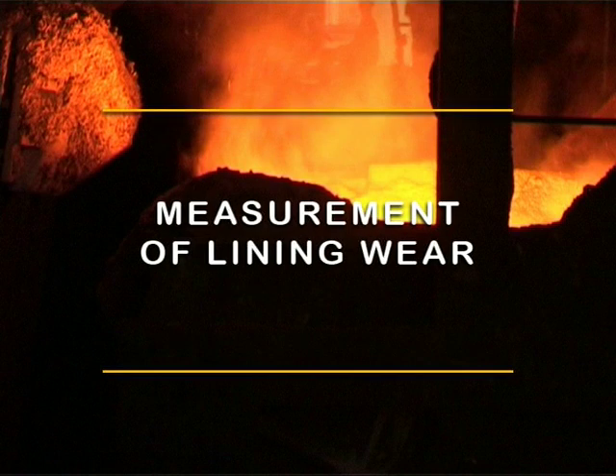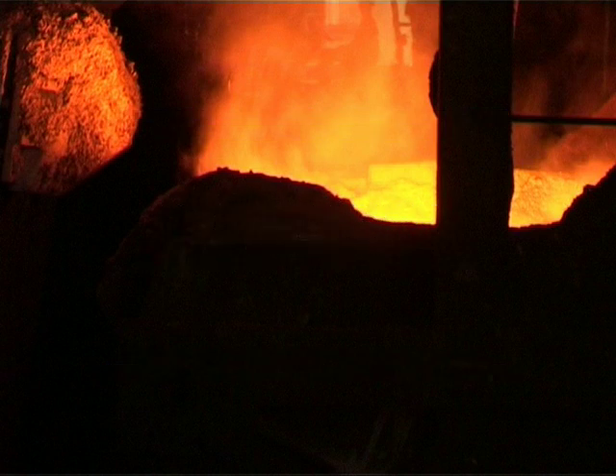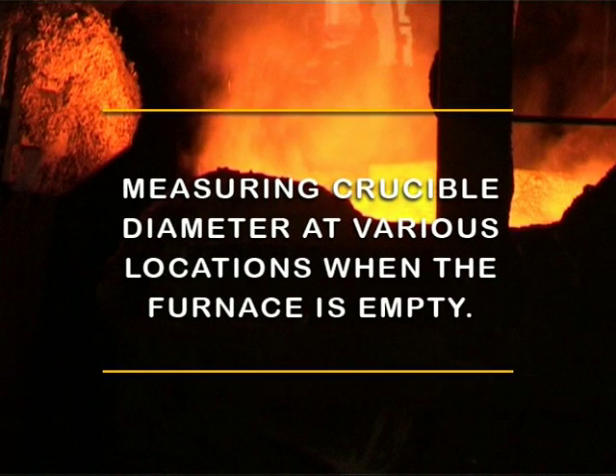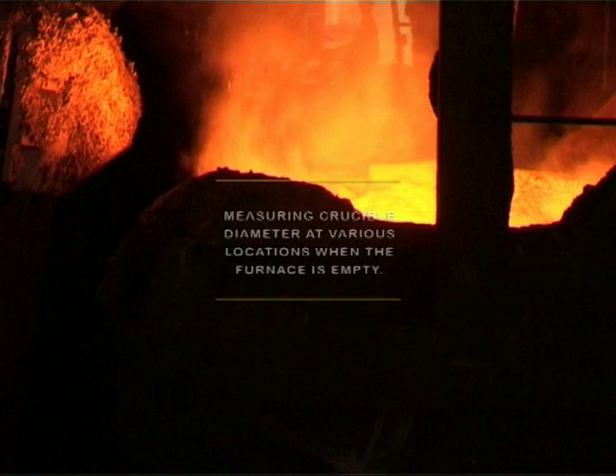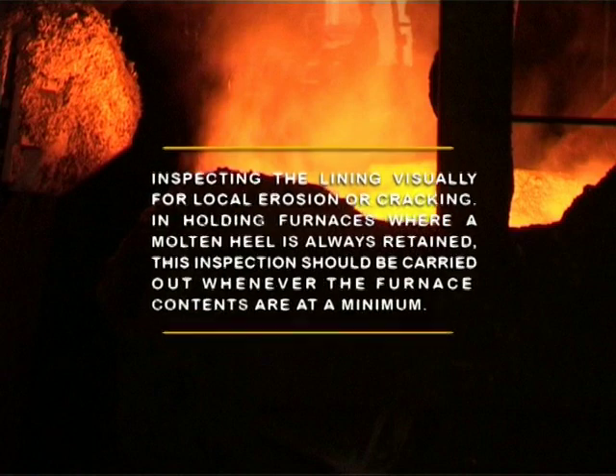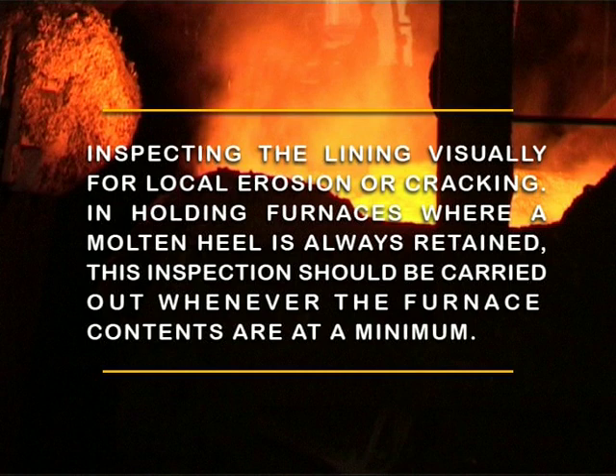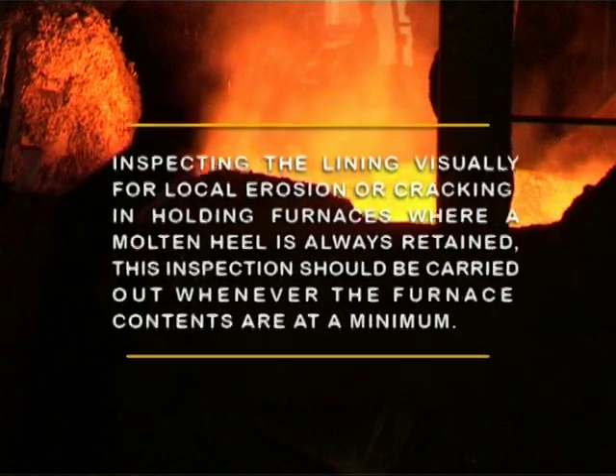Measurement of lining wear. It is very important that the furnace operator should be aware of the changing condition of the crucible at all times. This can be achieved by measuring crucible diameter at various locations when the furnace is empty, and inspecting the lining visually for local erosion or cracking. In holding furnaces where a molten heel is always retained, this inspection should be carried out whenever the furnace contents are at a minimum.